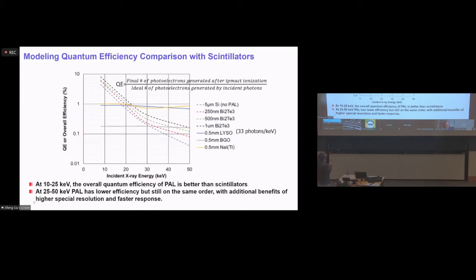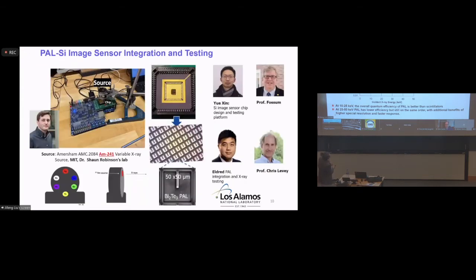Okay, so how does this compare to scintillators? This is, again, Eldridge's analysis. It shows that with our current PAL layers at photon energy below 25 keV, they perform better than scintillators. If you go to a higher energy like 50 keV, the quantum efficiency decreases to some extent, but you get the benefit of higher spatial resolution and also faster response time. So it's still a pretty good trade-off here.